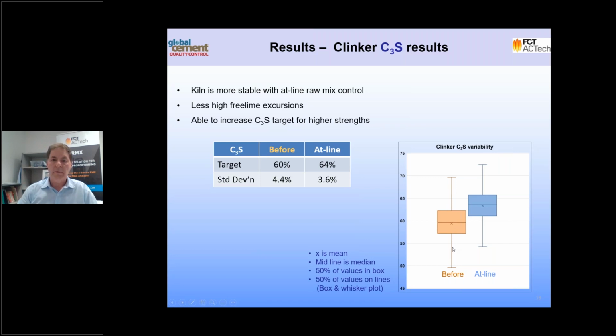So for this example, at this plant, before the online analyzer was implemented, we can see that the range of results is represented by the height of the orange box here, and we can see that that is reduced down. So what they've been able to do is reduce the variability at the same time as getting this additional increase in C3S, and we've also got the standard deviation results to confirm that over here as well. So the plant's been able to run at higher C3S with a reduced standard deviation at the same time, and that's something they just weren't able to do prior to the introduction of the raw meal analyzer.